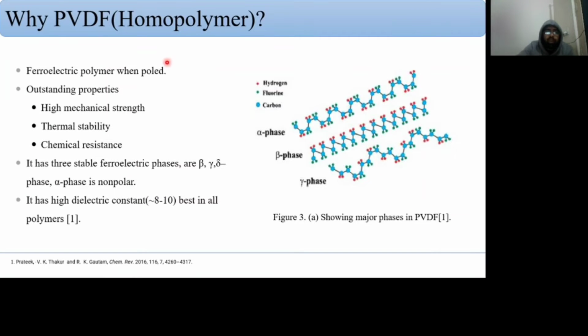Why are we using PVDF? PVDF is a homopolymer. PVDF is a ferroelectric polymer. It has very good mechanical strength, thermal stability, and chemical resistance. PVDF has alpha as a non-polar phase, and beta, gamma, and delta as ferroelectric phases, which are stable.